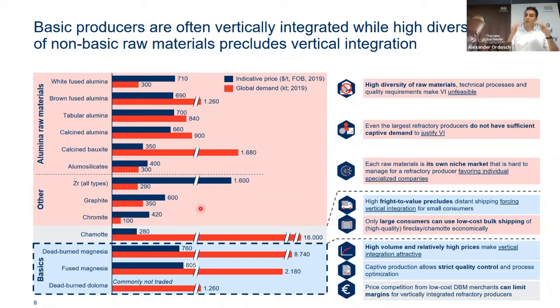But if we go a bit lower in this chart, we see that the big guys come in actually. So we see chamotte, so that's the processed fire clay. Global demand, 16 million tons. So about 3, 4, 5 times as much as the total other raw materials combined. And then also in the bottom, all the basic raw materials. So about 9 million tons of dead burnt magnesia, 2 million tons of fused magnesia, and about 1 million tons of dead burnt dolomite.